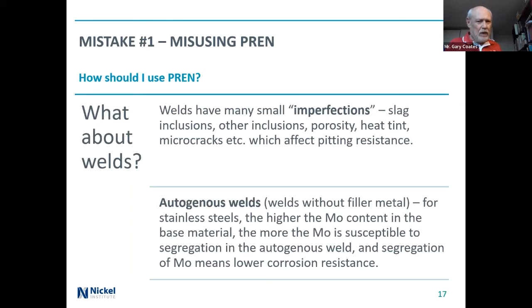So the weld metal may not be, in practice, as pit resistant as the base metal, and therefore that does limit the use of PREN. And I just also want to mention autogenous welds, welds without filler metal. For stainless steel, the higher the molybdenum content in the base material, the more the molybdenum is susceptible to segregation in the autogenous weld, the weld without filler metal. And segregation of molybdenum means lower corrosion resistance.